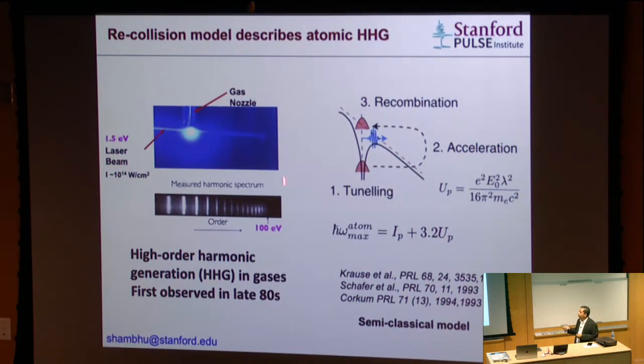And the maximum energy that you get, which is called the high energy cutoff, here in this experiment, this came out directly from my thesis. But the original experiment was, of course, done in the 80s. This is the high energy cutoff, the 100 eV. This is the maximum energy that I was able to produce with the parameter that I used at the time. And this scales quadratically with the electric field of the laser. Okay, so that becomes useful later.